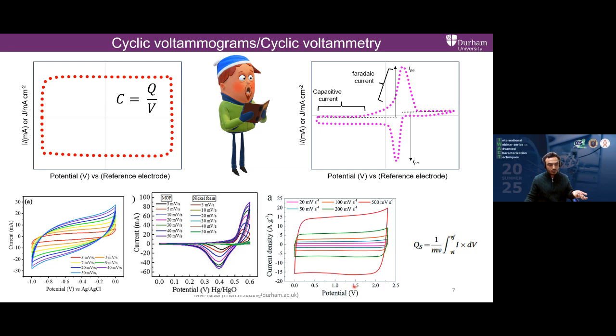So this is actually a 2 electrode cell, which is characterized at different scan rates, and then was further analyzed accordingly, whatever you are interested in. So that's the clear difference between 2 electrode and 3 electrode. Whenever you see in the literature that a potential is presented against some specific reference electrode, that's 3 electrode. If not, it is understood that this is coming from a 2 electrode cell.